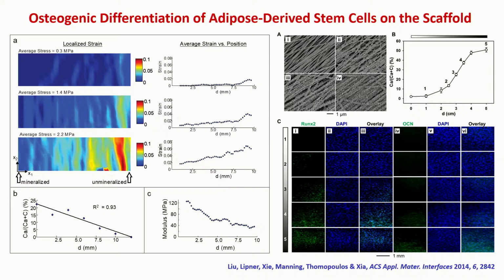Specifically, we expect formation of osteoblasts in the region with the highest density of mineral. So this is from RUNX2, which is a Runt-related transcription factor 2. It's an early marker for osteoblasts. So you can see from position 1 to position 5 along this curve, indeed, you have a gradual increase in differentiation of the stem cells into osteoblasts.